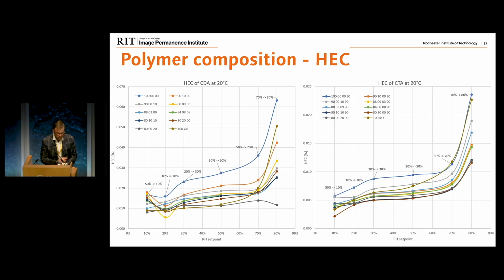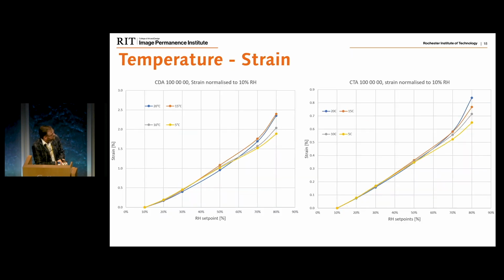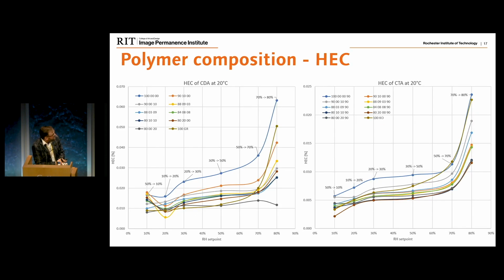Now, when you calculate the humidity expansion coefficient, which, remember, those are graphs of the rate of change, you can see that, first of all, again, you can see how well the polymers sort themselves by the amount and type of plasticizer. You can also see that the response at each step, the response of the triacetate, there we go, it's about a third of what you're getting in the diacetate. And you can also see the nice linear response.